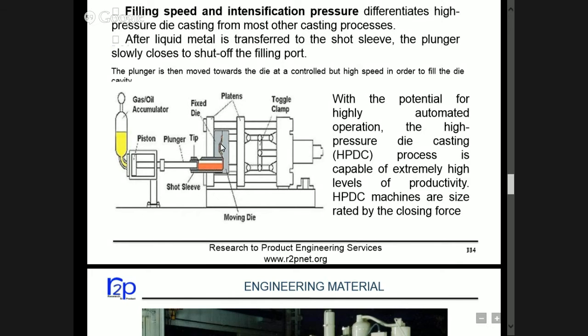the molds are closed, right? There is no place for any air entrapment to go away in the HPDC process, right? So in HPDC, the air is entrapped on the surface. So microporosity in HPDC is much more as compared to other processes. If you do heat treatment, the air which is inside the casting will come out, making blisters or pores, so the casting itself will become bad. So HPDC castings are used without any heat treatment.